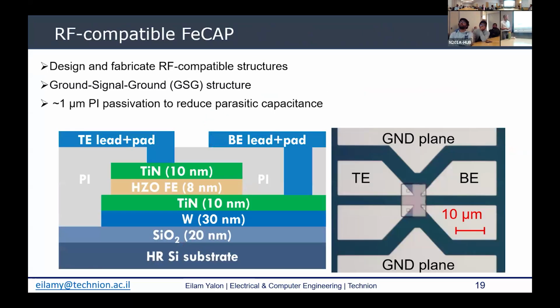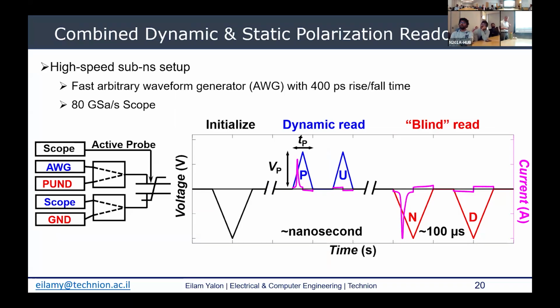So to probe this short time scale, we fabricated smaller area, RF-compatible structures. We're using high-resistivity substrates and transmission lines with pads bounding the ground, and smaller area capacitors. And now we're using another slightly modified measurement scheme. We again initialize the film to a known state. Then we apply 2 nanosecond scale triangular pulses, and we read the current within this pulse.